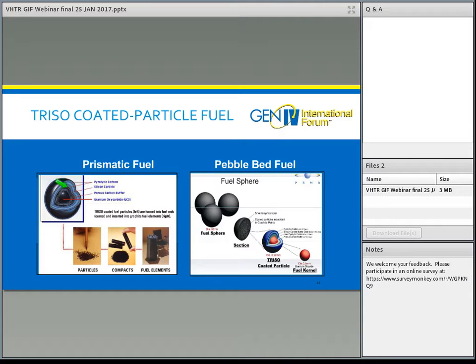Both on the inside of the silicon carbide, which is shown here as the light gray layer, and on the outside of that is a pyrolytic carbon layer, which in the construction of the particle helps the different layers to adhere together and to keep their integrity during the fuel manufacturing process.